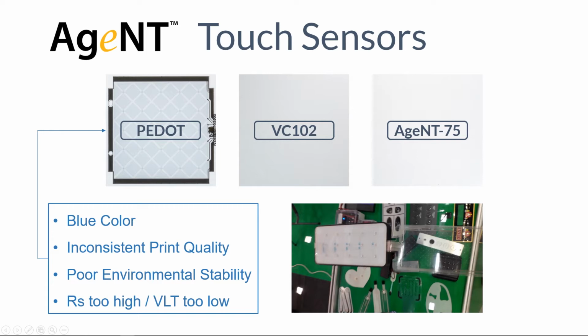So we have a two-pronged approach to attack PEDOT. First is to introduce a carbon nanotube only ink product that can be printed onto conventional plastic films. This product will have similar sheet resistance and transparency to PEDOT, but has neutral color, prints very consistently, and has outstanding environmental stability. So this product is coming to market in Q1 of 2020. And we ultimately expect to trade up customers that adopt this solution to the carbon nanotube hybrid solution, AgeNT-75, which also offers much lower sheet resistance and much higher visible light transmittance.